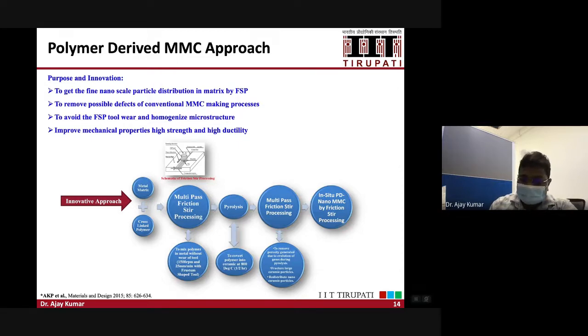but in situ it can be converted into the ceramic phase during the pyrolysis. During the pyrolysis you will see a lot of gas evolution due to the temperature and reactions. Those gas evolutions will create voids or micro voids in the material, so it will become porous, okay? If it becomes porous, we cannot use that material. So you have to remove the porosity, and you do the multi-pass FSP process to remove the porosities and redistribute the particles at the nanoscale. Okay, so this is the approach, and this idea we published and patented in 2015.